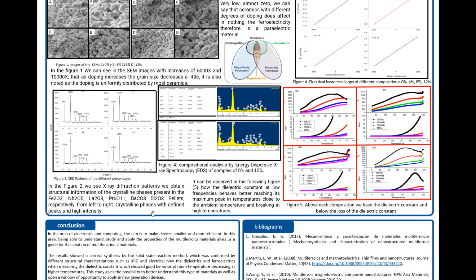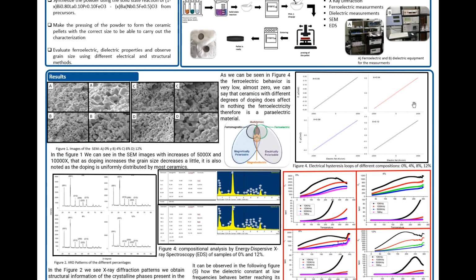After that we do the analysis of the XRD diffraction. In the patterns we observe information from the iron oxide, niobium oxide, lanthanum oxide, praseodymium oxide, barium carbonate, and bismuth oxide, to the left and to the right. And after we do the characterization of the electric measurements using the ferroelectric equipment and obtain these hysteresis loops. As we can see, the ferroelectric behavior of these materials is not very good, and we can conclude this is a paraelectric material.